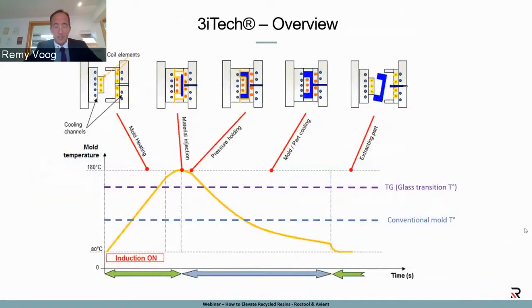So this is how it works. If you take, for instance, a PC, you go from 80 to 180 degrees. Let me take my pointer. This is time and this is temperature. In conventional molding, you'll have a more or less stable temperature on the molding surface, whereas in Roctool, you have the luxury to change your temperature dynamically. So you're going to go above the glass transition temperature, and then you're going to do what you have to do. You're going to inject your part, you're going to compact it.